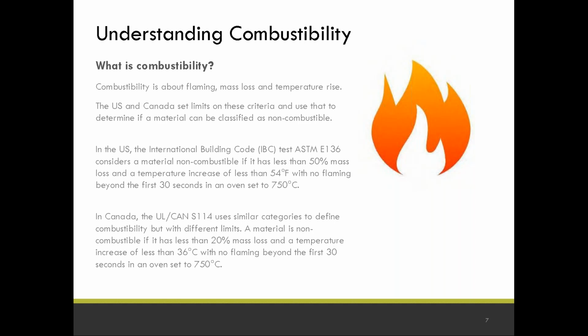In Canada, the S114 uses the same three criteria and actually the same test apparatus, but their limits are: a material is non-combustible if it has less than 20% mass loss, a temperature increase of less than 36 degrees C, with no flaming beyond the first 30 seconds. So as you can see, a material can actually be considered non-combustible in the US and combustible in Canada, or even vice versa.